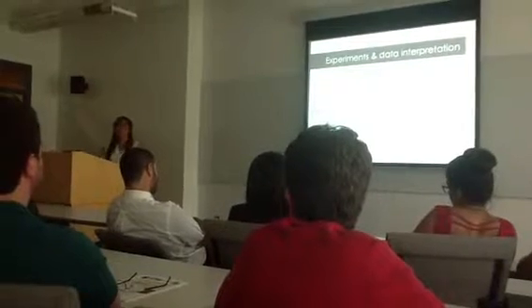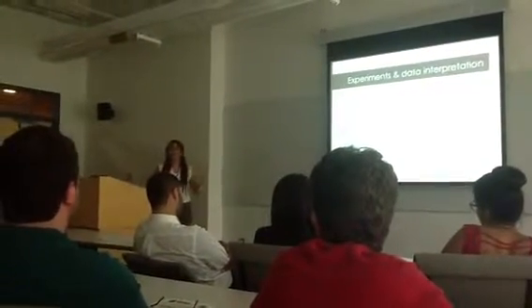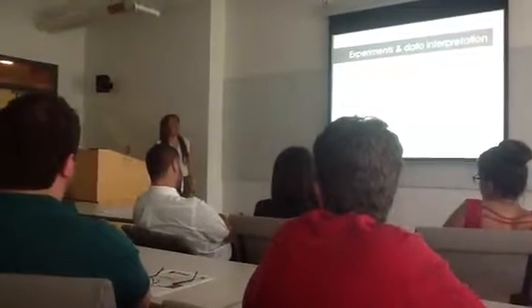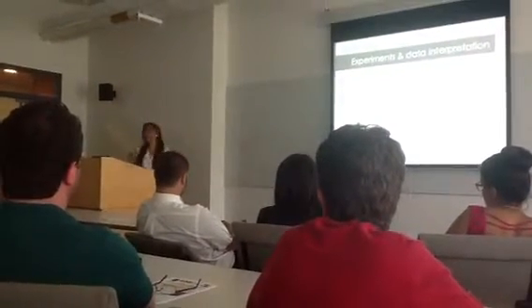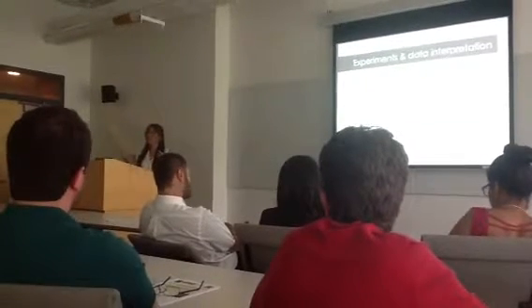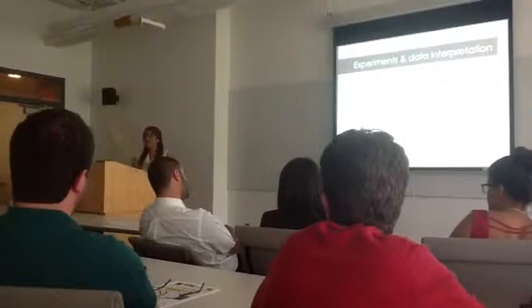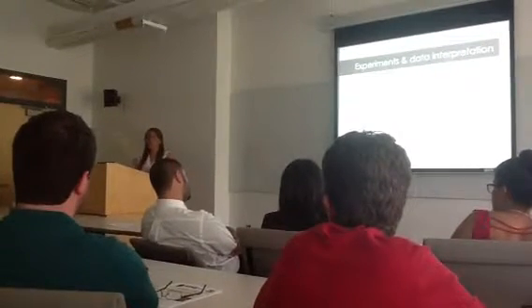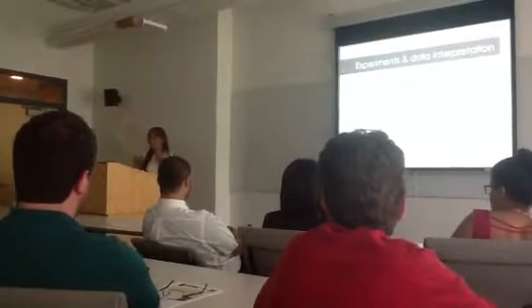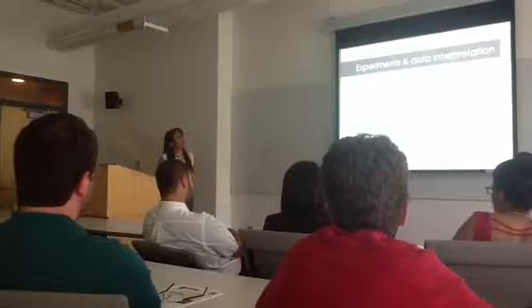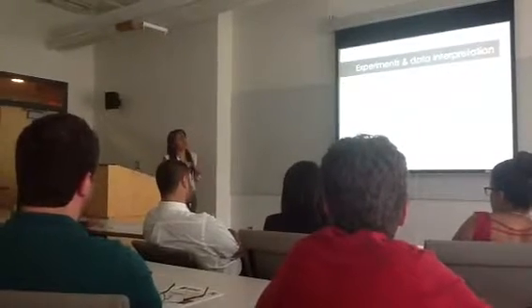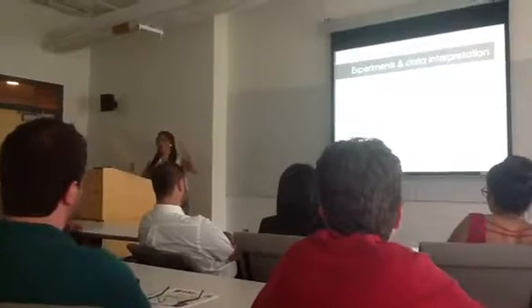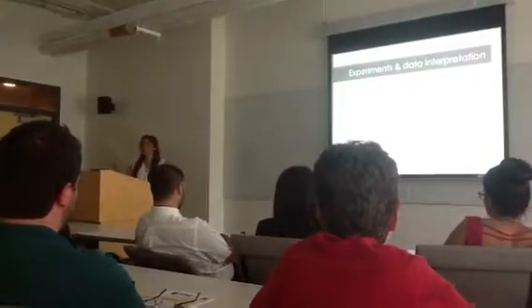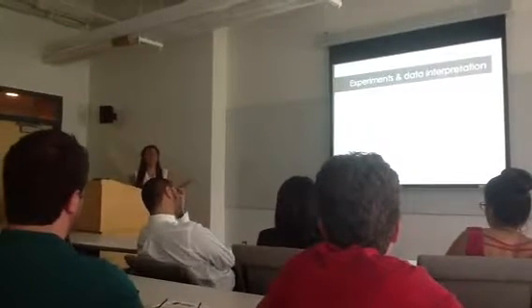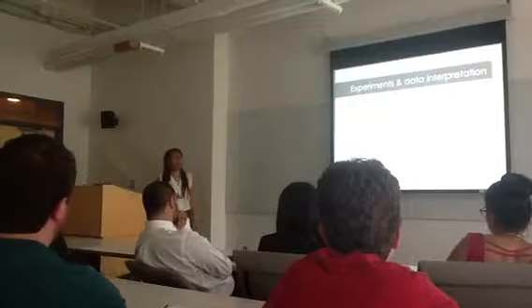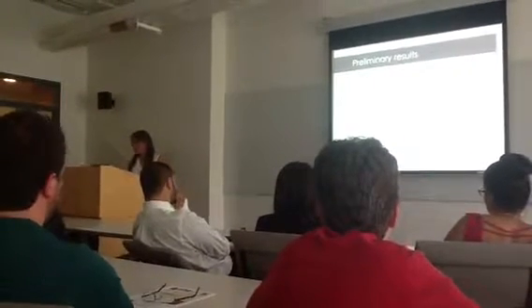And we are looking for 3 main points from the data that I obtained from these experiments. That is the current density at 0.4 volts. That value is the least amount of potential that I need for the optimum conditions for the oxygen evolution reaction. And also I want to look for the potential at this current density, because previous research has shown that this current density is correlated with 10% efficiency in solar water splitting devices. And finally, we want to look also for the Tafel law that I'm going to explain in the next slide.